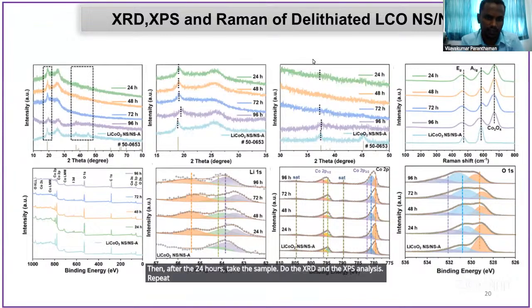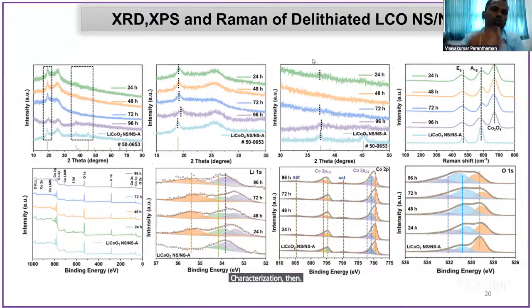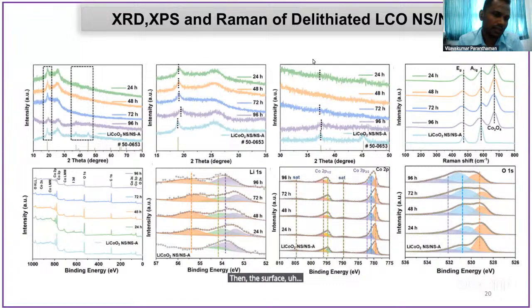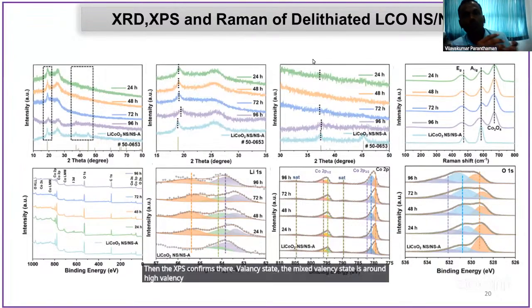Repeat all the characterization. Then you see the variation: there is a shift between the initial bare material as well as the delithiation material. The lithium removal, with the peak shifting to the lower side and higher side, confirms the partial lithium has been removed from the LiCoO2. Then the surface element analysis, the XPS survey structure, confirms all elements are present. Then the XPS confirms the valency state. The mixed valency state is around high valency states like Co3+ to Co4+ because of the lithium removal.